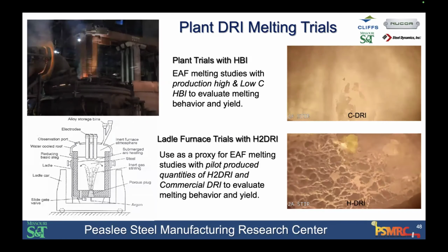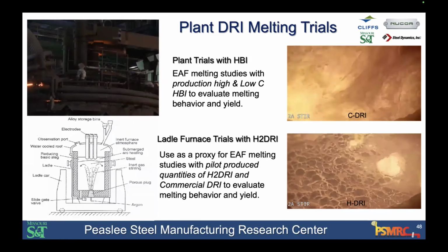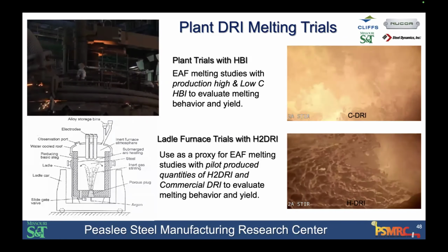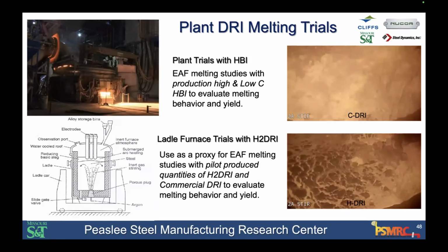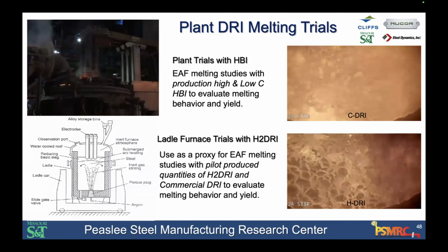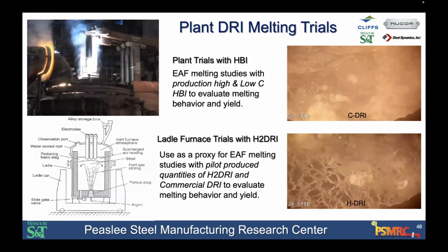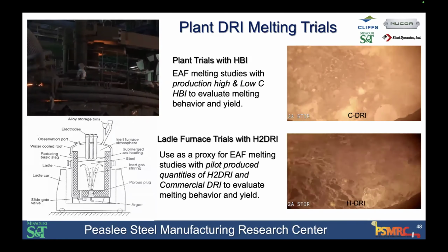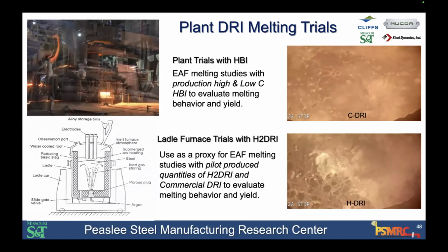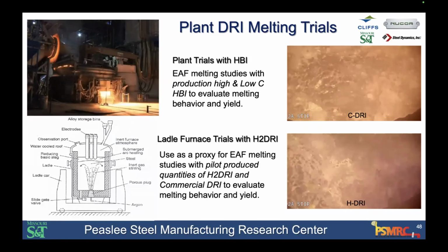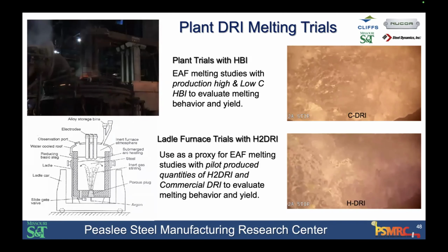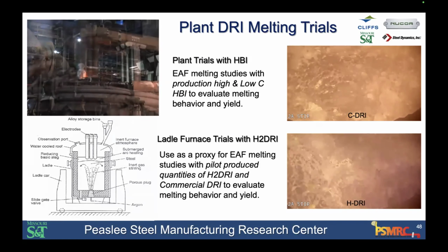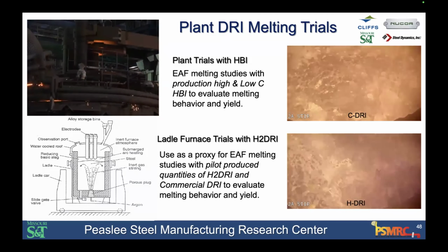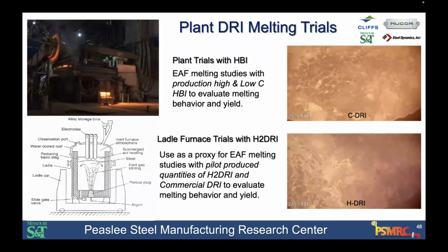And you can see with the carbon-bearing materials, you get a lot more activity in the slag and the foaming. And this is one of the big challenges that needs to be overcome with hydrogen-reduced DRI, is that it doesn't provide that source of gas evolution that causes enhanced stirring and enhances the foaming in the slag in the electric furnace environment. And so other means of controlling that have to be developed.